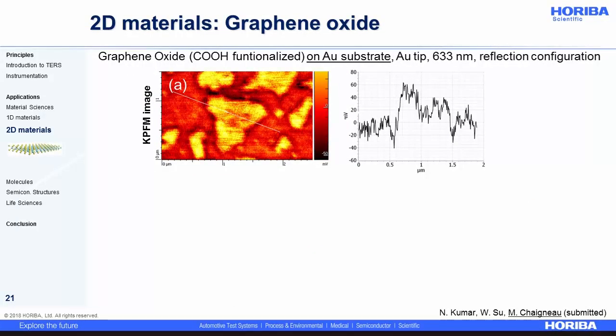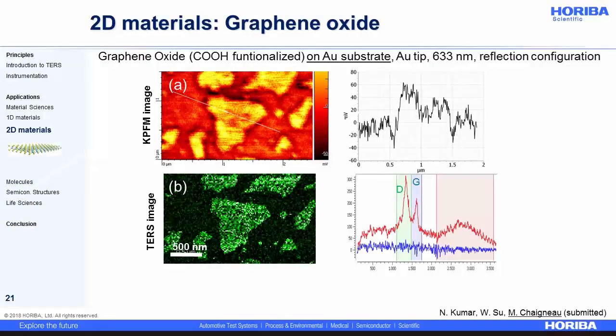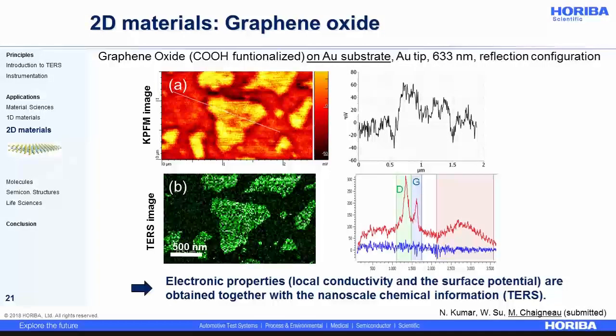This interesting behavior of the wrinkles in graphene oxide sheets led us to investigate whether all the electronic properties of graphene oxide, such as its surface potential, could be linked to the chemical information accessible with TERS. The contact potential difference, or the surface potential, is here obtained with Kelvin probe measurements in figure A. It is showing locally a Fermi level variation that can be put into contrast with the defect density revealed thanks to the TERS map. So here again, we see that we can combine electronic properties through the local conductivity, or here the surface potential map, together with the nanoscale chemical information thanks to TERS.